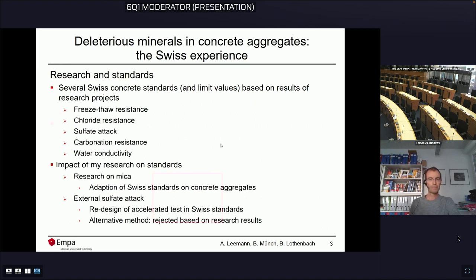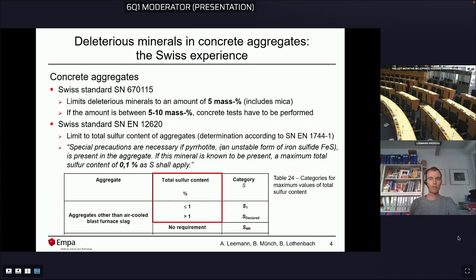Next, please. So what are we using for concrete aggregate standard-wise? So we have a Swiss standard, 670 115. It limits the amount of deleterious minerals in the aggregates to 5 mass%, and this includes mica. If the amount is between 5 to 10 mass%, concrete tests have to be performed to show that the concrete reaches defined performance criteria.